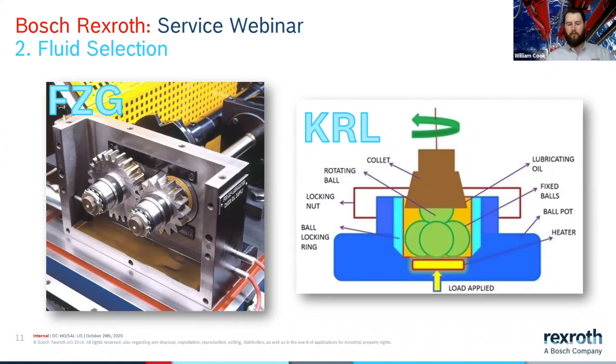As shown on the left, gears are put through a progressive load cycle. They are weighed, tested, then inspected for damage, re-weighed, and put through the next load test until failure. According to common fluid standards, FZG should be at a fail stage 10 minimum.